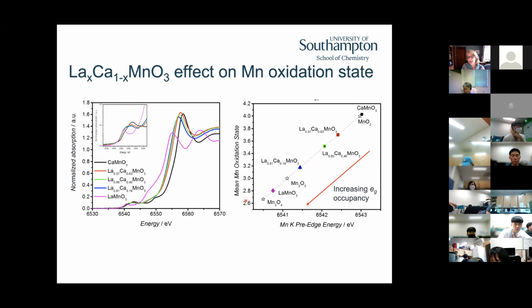Let's look at the change of the oxidation state of the manganese as we change the composition, because we would expect that to be the case. So the lanthanum manganate is sitting down here when we have that increased EG occupancy, and the calcium manganate is sitting up there. So these are our samples.